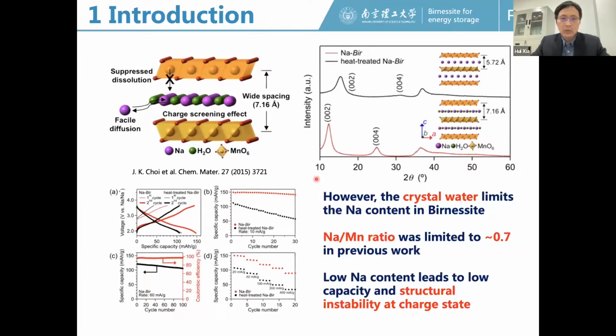But however, the crystal water also has some disadvantages. We know that at the interlayer, the sodium ions and the crystal water will compete to occupy the interlayer positions. So if we have too much crystal water, the sodium content will be very low. So in the previous work on Birnessite, usually we have a very low sodium content, and the sodium to manganese ratio is usually about 0.3 or 0.4, and the highest value is about 0.7 in the previous work.